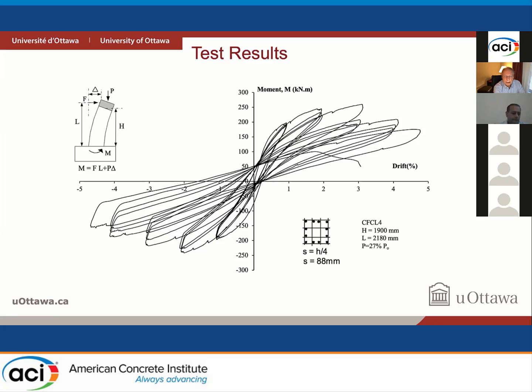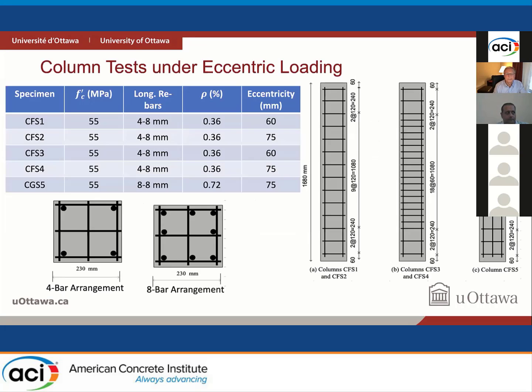On the compression side, we were able to attain about 0.8% strain before bars buckled, and on the tension side, we were able to go up to 1% strain. So what was interesting was the observation that bars were able to develop significant compression strain, which was compatible with crushing of concrete, even though in our current CSA S806 standard, we disallow compression capacity of reinforcement when we design columns with CFRP bars. Now let's look at column tests under eccentric loading.